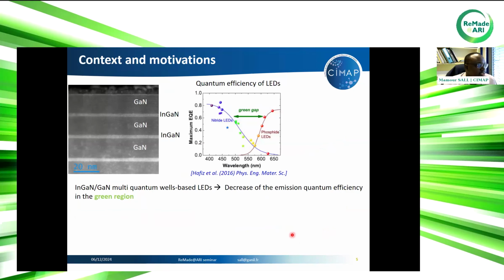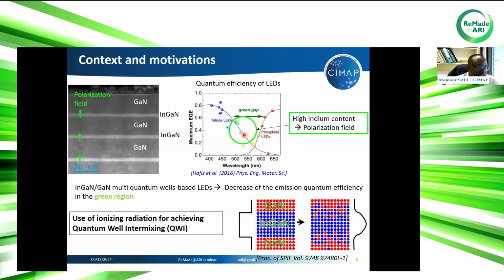So how to do this? This is an image of an indium gallium nitride multi-quantum well. It is made of alternating layers of gallium nitride and indium gallium nitride. And this system is currently used for light-emitting diodes in the blue region with very high efficiency. But the problem comes when we want to emit light in the green region, because the efficiency drops. This is due to the fact that if we want to emit green light, we need to increase the indium content in the indium gallium nitride quantum well here.